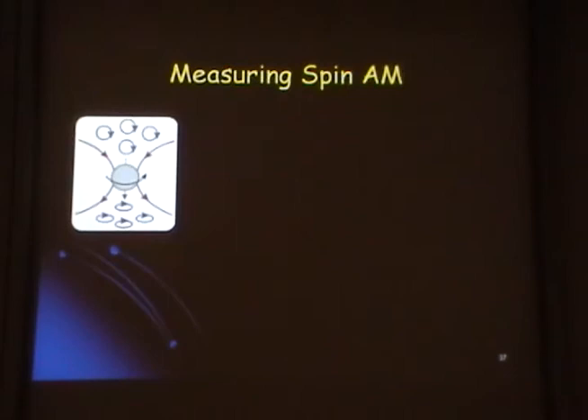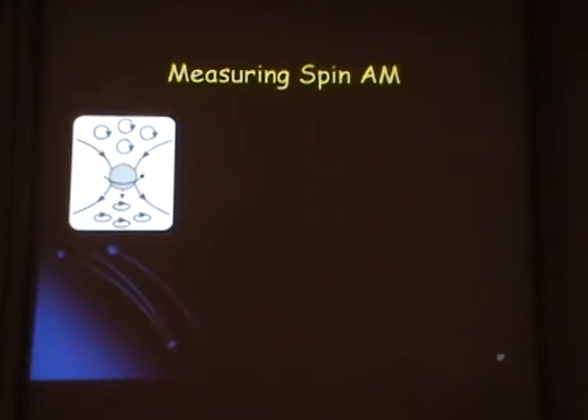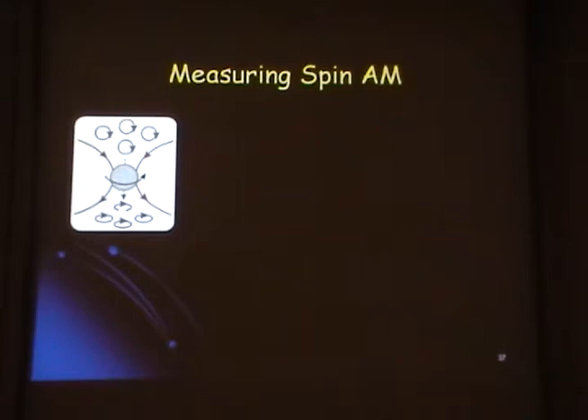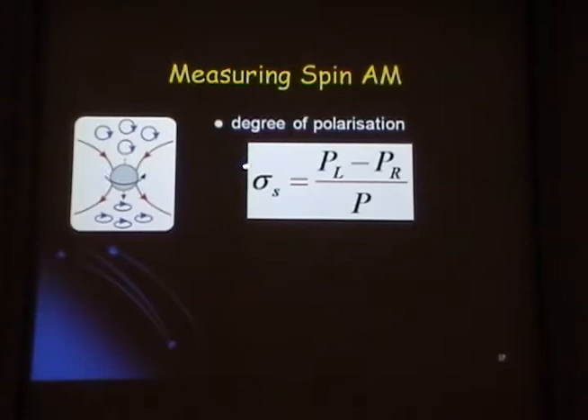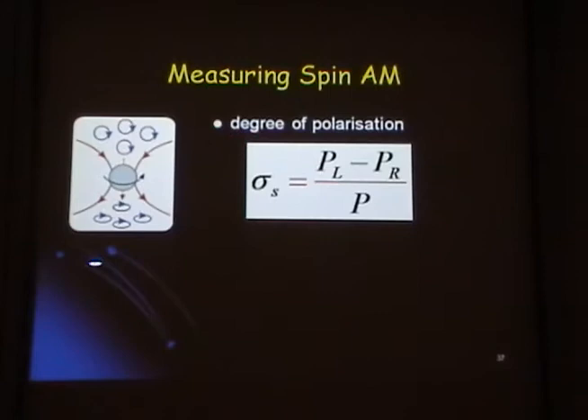So in summary, circularly polarized light hits our vaterite particle, I transfer spin angular momentum, and the state of polarization changes, so the transmitted light may now be elliptically polarized. I assume that I can collect all this light and measure the state of polarization. So the degree of polarization is the transmitted left-handed minus right-handed circularly polarized light, divided by the incoming power of the beam, and that gives me the degree of polarization of the transmitted light. How do I do it?